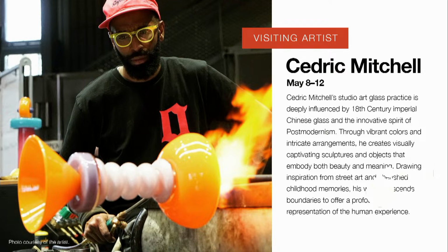So I'll talk about some of the temperatures we're dealing with here. When the glass comes out of the furnace, 2125 degrees Fahrenheit. The reheating chamber we're using right there, the glory hole, it's about 2100 to 2300 degrees Fahrenheit. You'll see us using these torches sometimes. The torches are anywhere from 3,000 degrees to about 5,500 degrees. The little small one right here, it's oxygen and propane. That one is the hottest thing in here, and that's used for getting one specific area really hot, and that one burns about 5,500 degrees Fahrenheit. Hot enough that you can actually boil the glass.